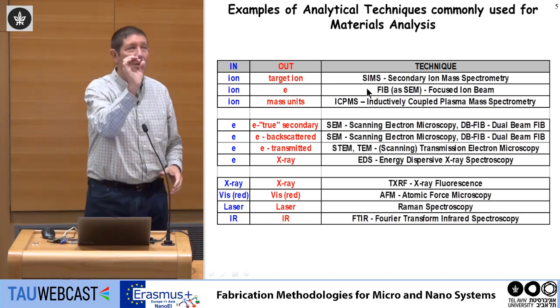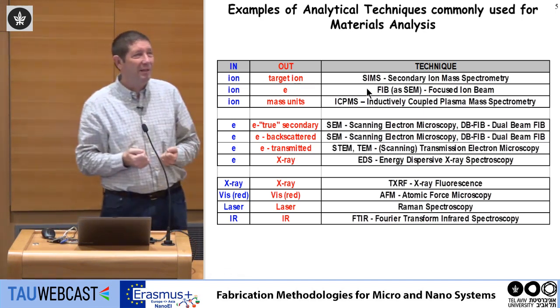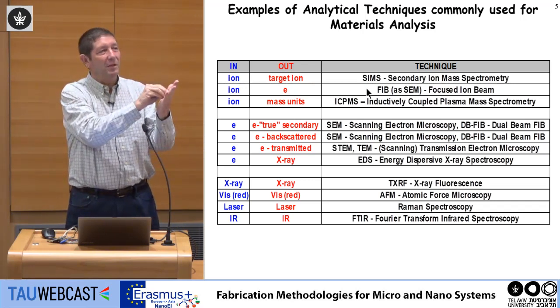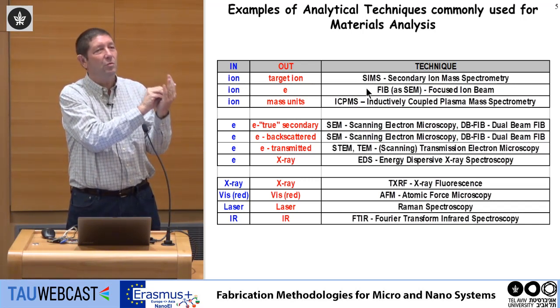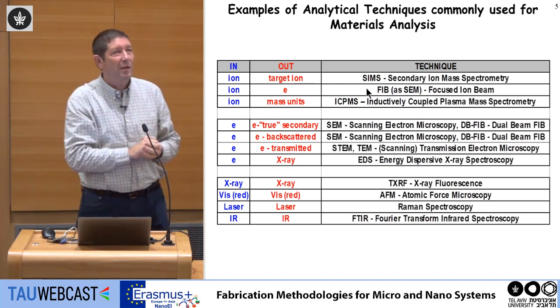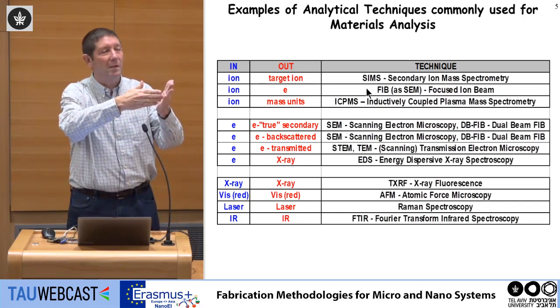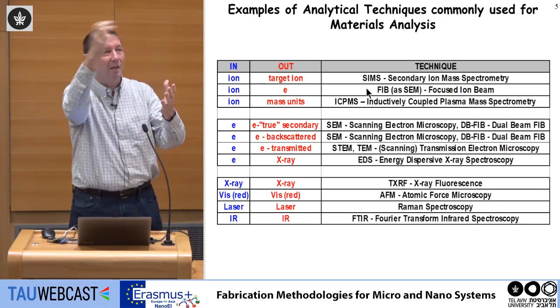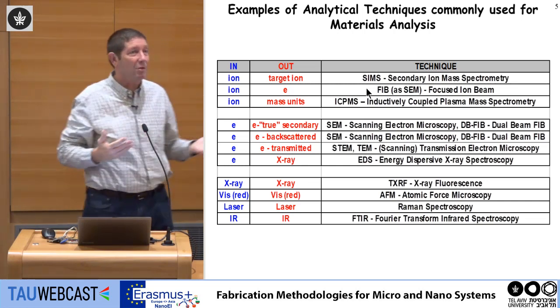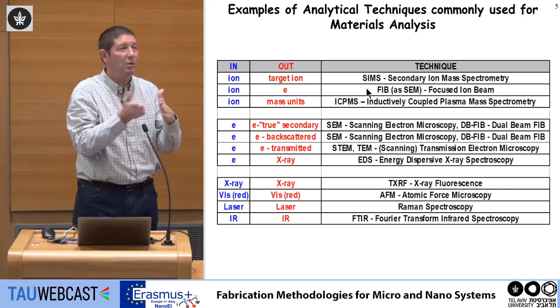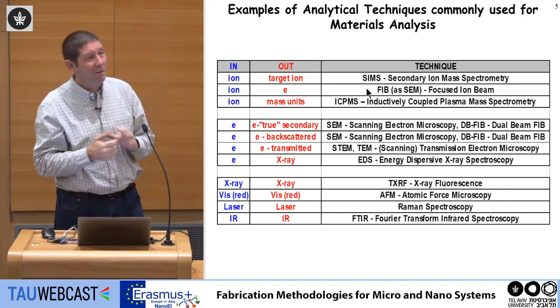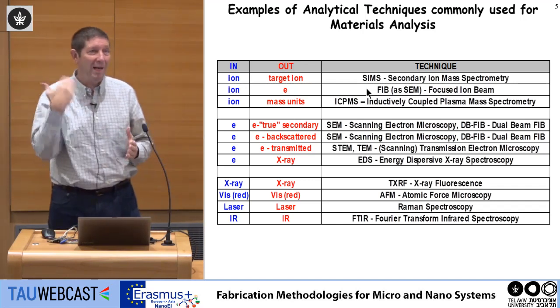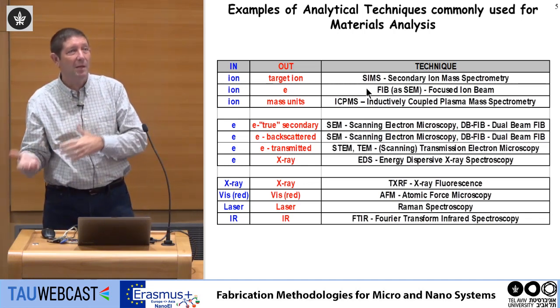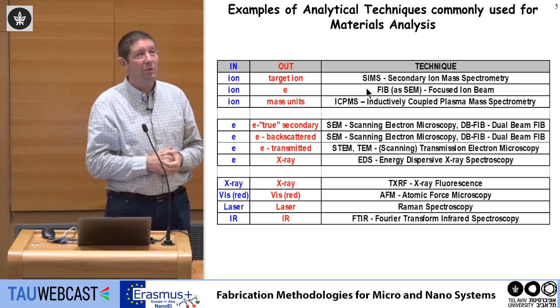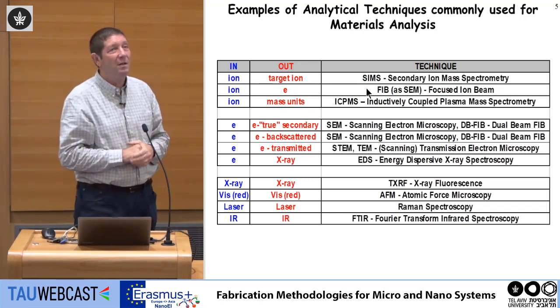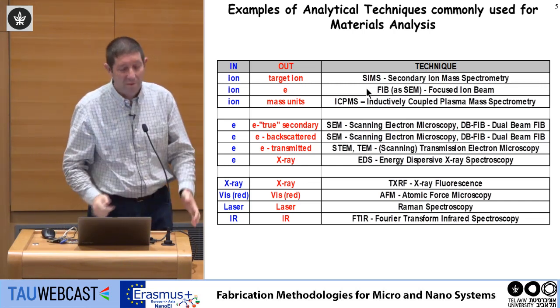I take a focused ion beam, which is what the name says. And the beam hits the silicon, and because I can transfer energy to the electron, some are being emitted. So I can, for example, take the silicon, the ion beam, and scan the wafer and look at the scattered electrons, and actually generate a map, an image of the surface based on electrons emitted due to interaction with ions. It's similar to electron microscopy, but in electron microscopy we use electrons to generate secondary electrons. But I can also use ions to generate secondary electrons, and this is a different kind of image, which is, by the way, very sensitive to grain boundaries, and it's very nice to look at crystalline structure.